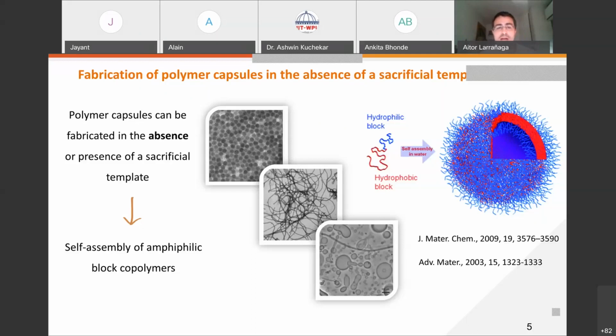As you may know, amphiphilic block copolymers will have at least one hydrophilic and one hydrophobic block. So when you put this kind of amphiphilic block copolymers in water, they tend to rearrange themselves. They tend to self-assemble so that the hydrophilic block will be oriented towards the aqueous environment, whereas the hydrophobic block will be oriented towards the center of the membrane, a bilayer membrane. Because of their similarity to the naturally occurring liposomes, sometimes we call this kind of synthetic structures polymersomes.